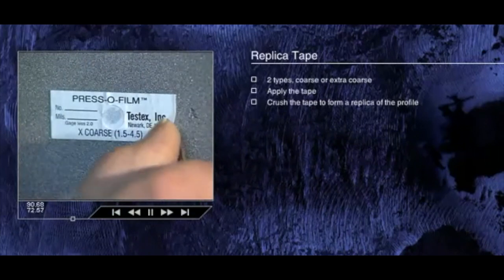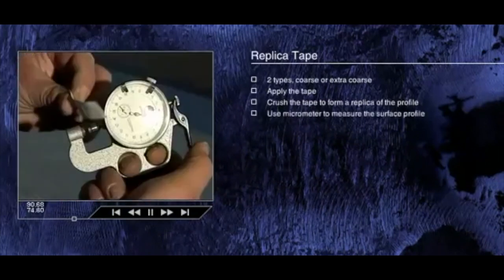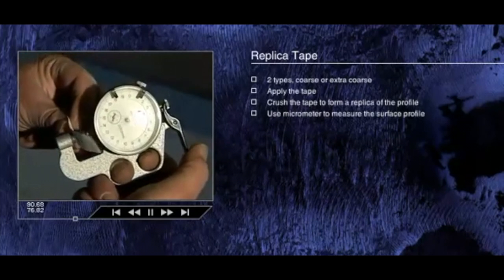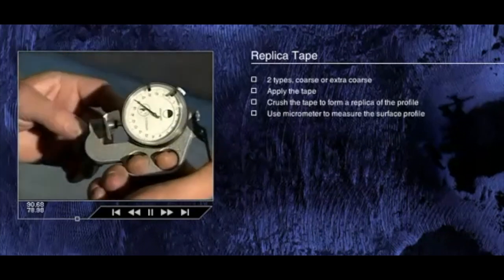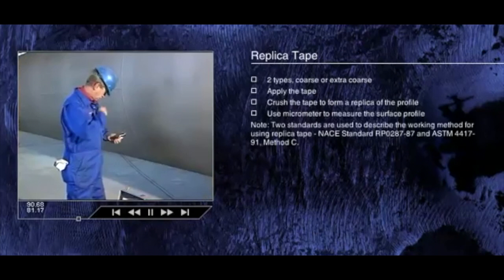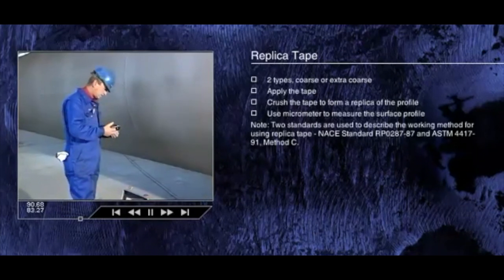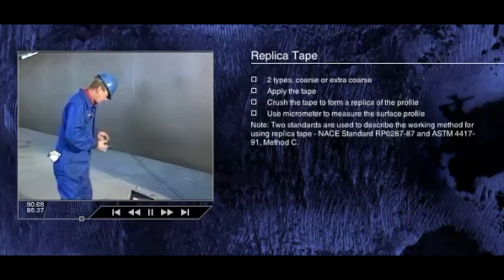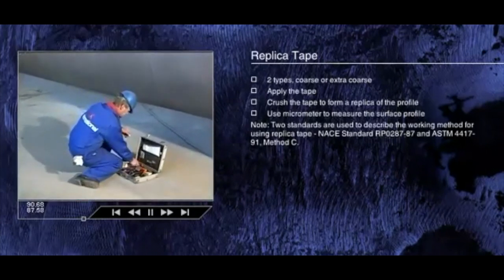The tape is removed from the surface and an anvil micrometer is used to measure the thickness of the foam and the plastic. The thickness of the mylar film, 2 mils, 50 microns, is subtracted from the micrometer reading, and the result is the depth of the surface profile.